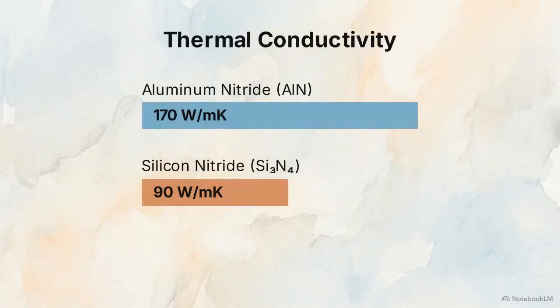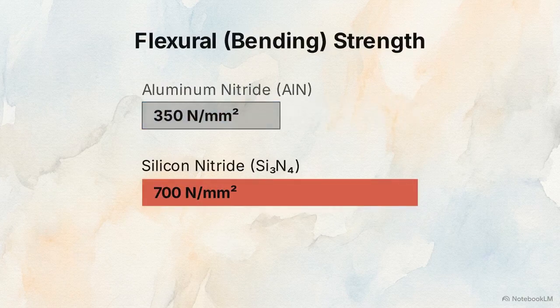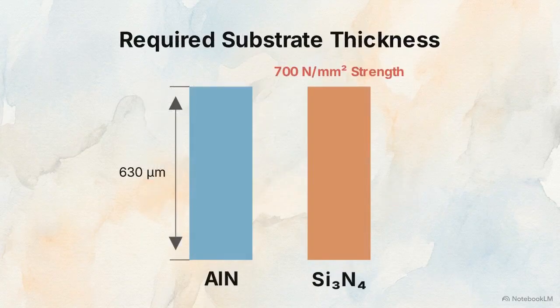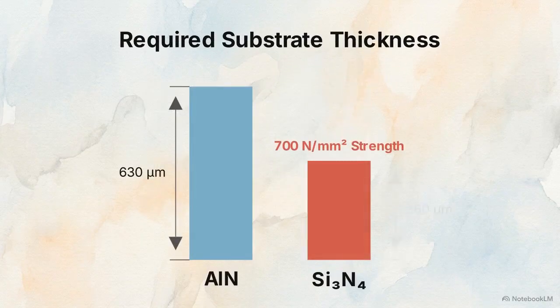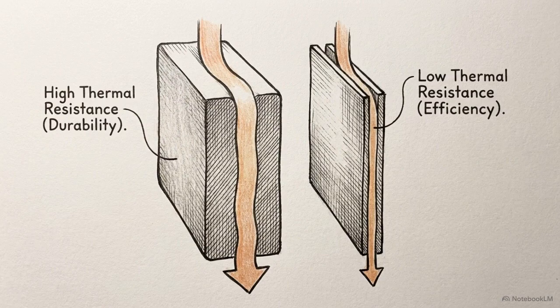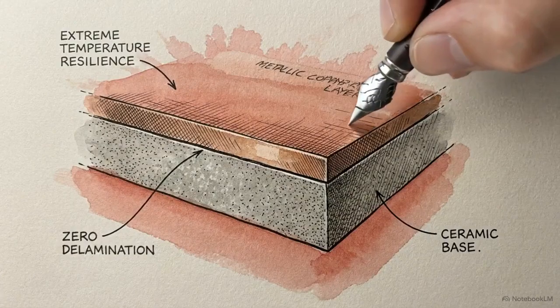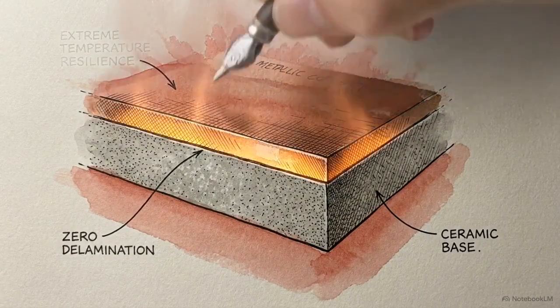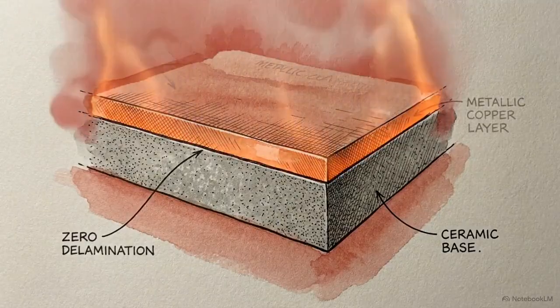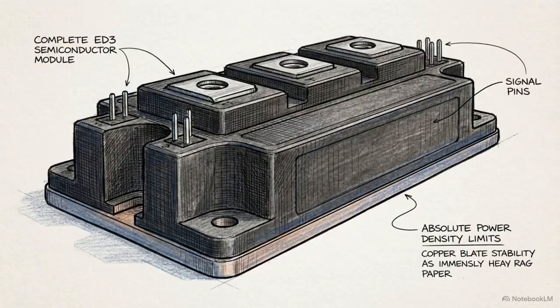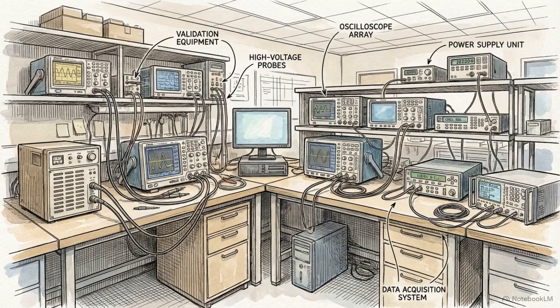Silicon nitride has a lower raw thermal conductivity of 90 watts per meter Kelvin than aluminum nitride. However, its massive bending strength of 700 newtons per square millimeter allows engineers to manufacture much thinner substrates, down to 360 micrometers. Because it is so thin, the silicon nitride substrate matches the overall thermal resistance of thicker aluminum nitride options while providing vastly superior mechanical durability. Empirical testing shows that these silicon nitride substrates survive well past 1,000 extreme temperature shock cycles with zero copper delamination. This structural integrity ensures that designers can push the silicon carbide module to its absolute power density limits without risking packaging failure.